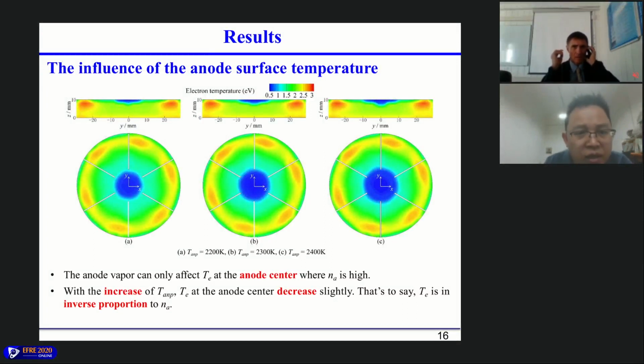And this is the electron temperature distribution. We consider different anode surface temperatures. Anode vapor can only influence the electron temperature at the anode center, because the anode vapor number density is very high there. And with the increase of the temperature from 2200, 2300, 2400, the electron temperature at the center decreases slightly. That is to say, the electron temperature is inversely proportional to atom density.